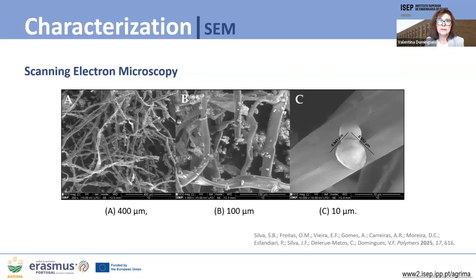We also evaluate the biocomposites by scanning electron microscopy to observe the morphology. As you can see, we have different magnifications. Here we have 400, 100 and 10 micrometers. As observed, the composition of our biocomposites includes fibers isolated from chestnut shell that act as a reinforcement agent of the polymeric matrix, composed also of starch granules, as you can see in picture C, with an average diameter of around 6 micrometers.